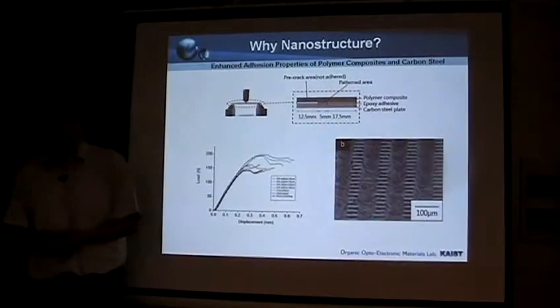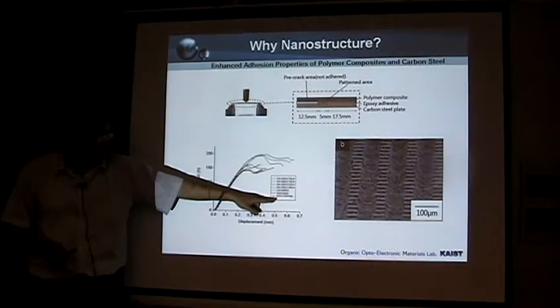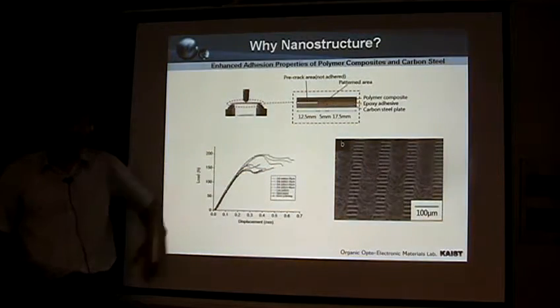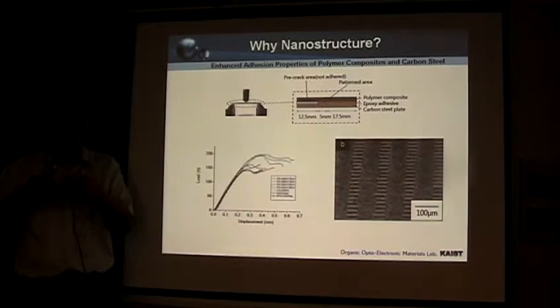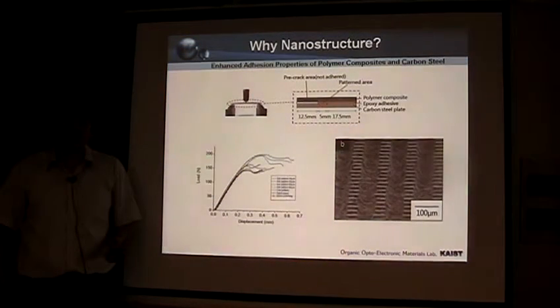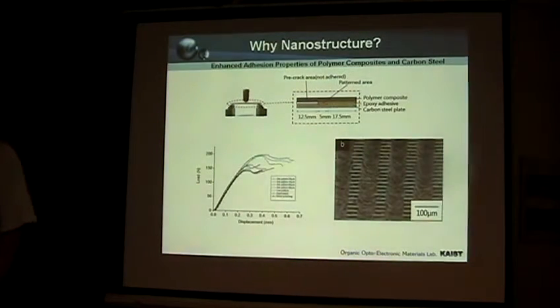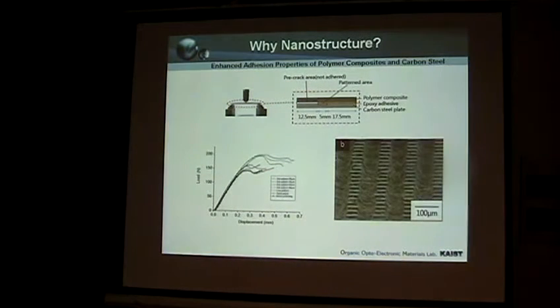When we put this kind of nanostructure on carbon steel plates, as you compare, I don't think you can see very well, this is like a mirror polishing. Sandpaper is the other way. And when we provide some nanostructure on the carbon steel surface, adhesion is really enhanced. So if you apply molecular assembling nanostructure to any surface, there is some possibility to enhance even mechanical properties. So there are many advantages, right? First, high data storage, very stable bio sensitivity and stability, control of orientation, formation of other inorganic materials, and also enhanced mechanical properties.